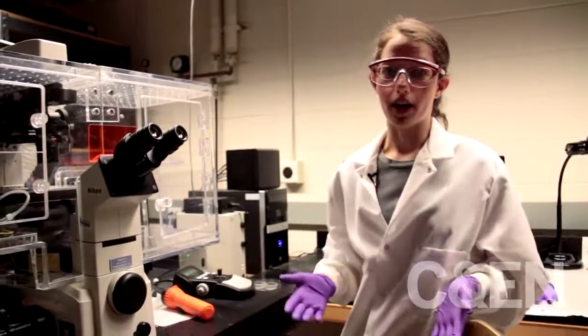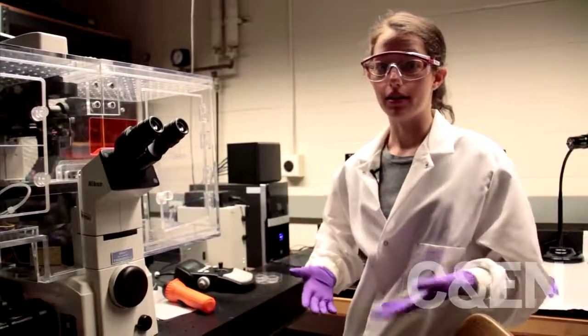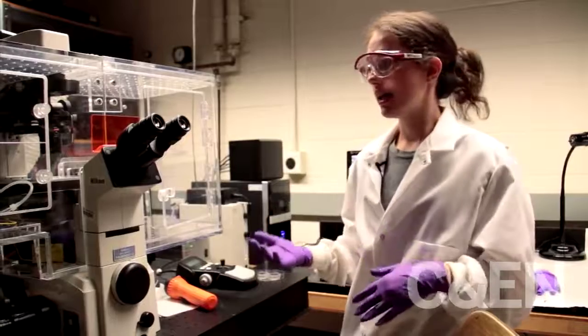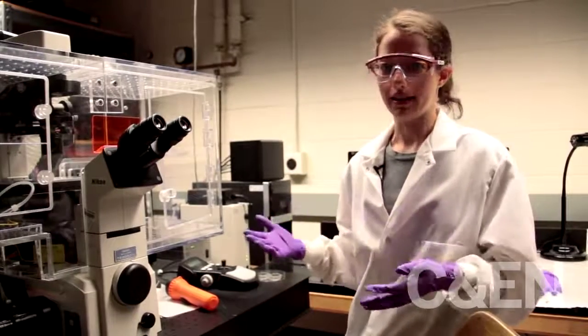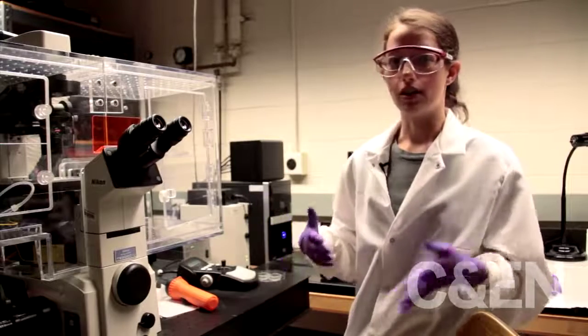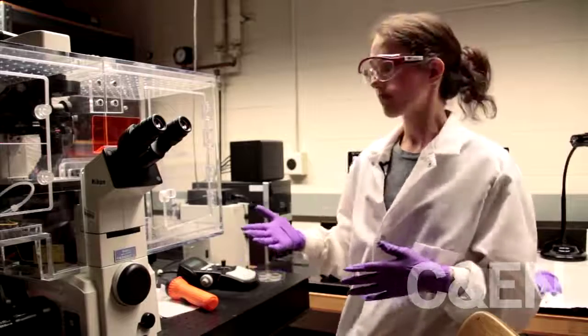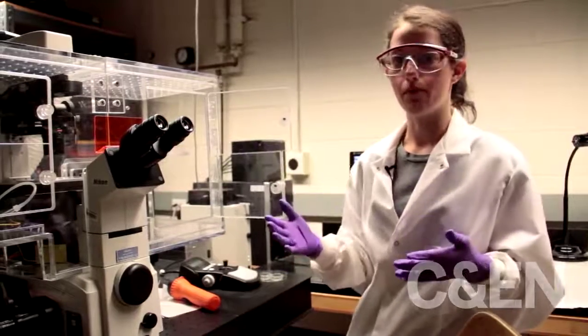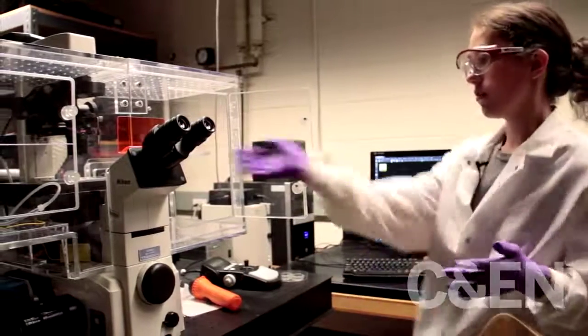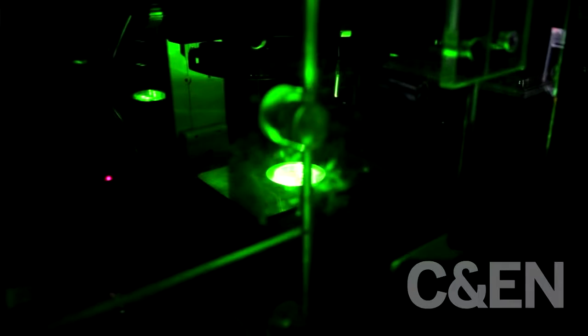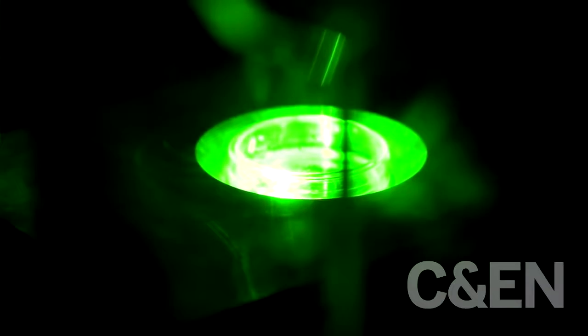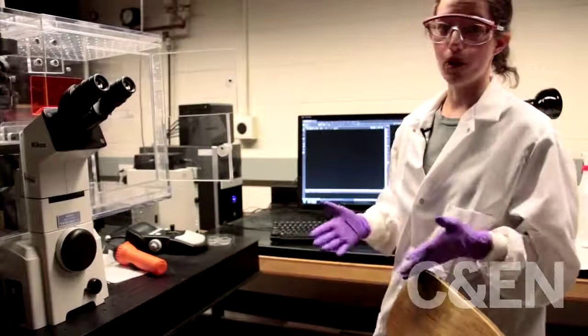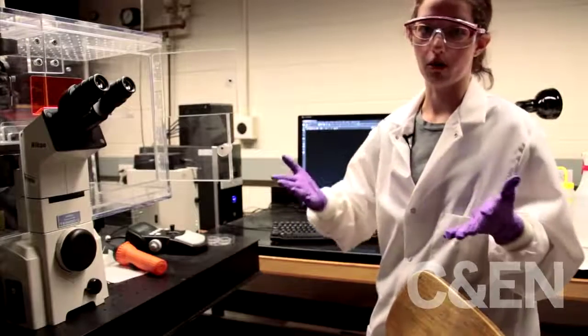Once we have our quantum dots in water, we can activate them with antibodies, which are what we use to target the cancerous cells. And then we incubate the quantum dots with various different cell lines to see whether or not the quantum dots will adhere to the cells. And so here, when that's all finished, we look at them with the microscope. And we just put it on the microscope, and then we are able to view the cells in a variety of different manners, both with the phase contrast, which is what you see normally with your eye, and also with different fluorescence. Right now we're looking at images of the cells, cancer cells, that have been targeted by quantum dots.